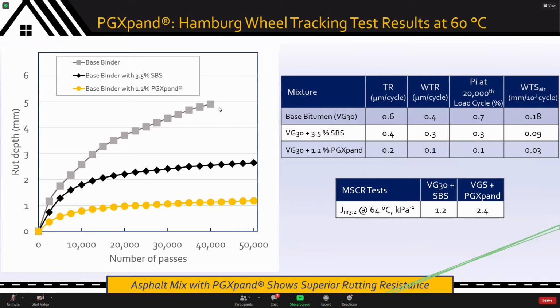Here it is VG30. The black line is for the same binder with 3.5% of SBS, and the golden curve is one for the binder with 1.2% of PGXpand. The selection of these 2 dosages was based on the fact that this was the dosage, 3.5% SBS or 1.2% PGXpand, that was responsible for getting the base binder to a softening point of 72 degrees softening point.